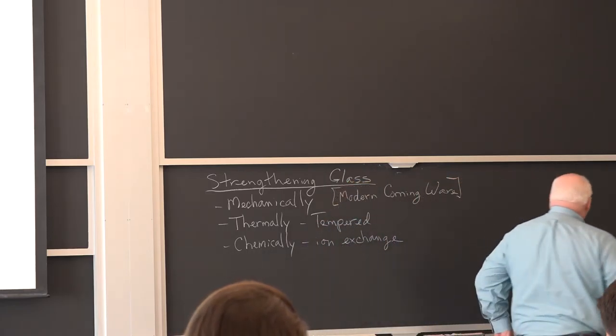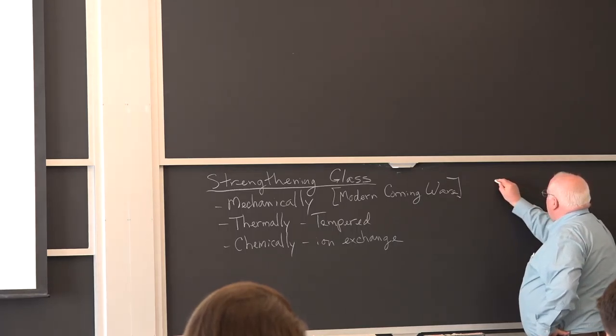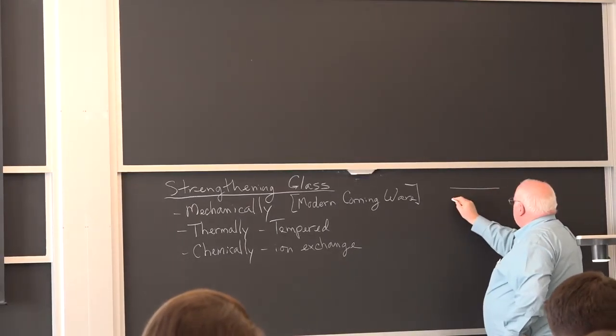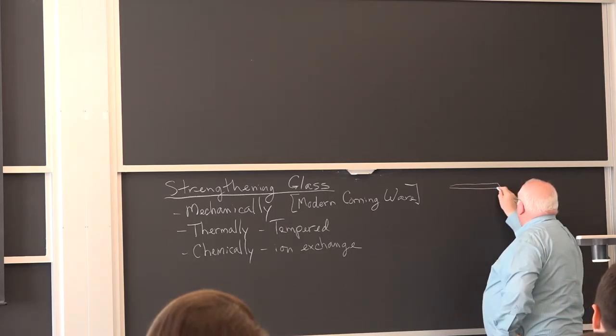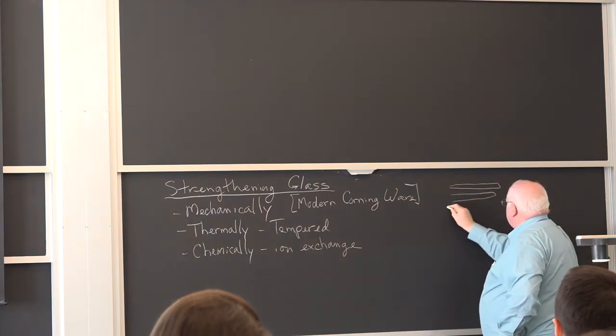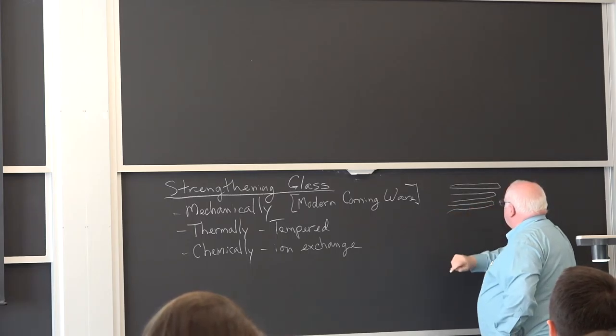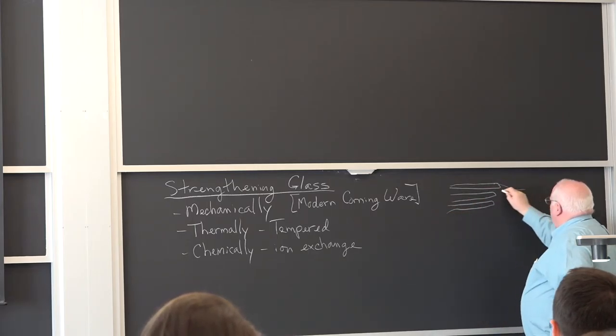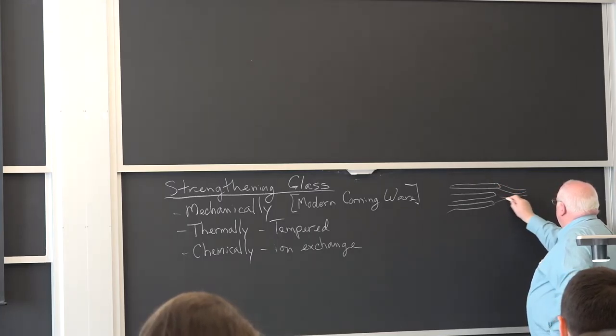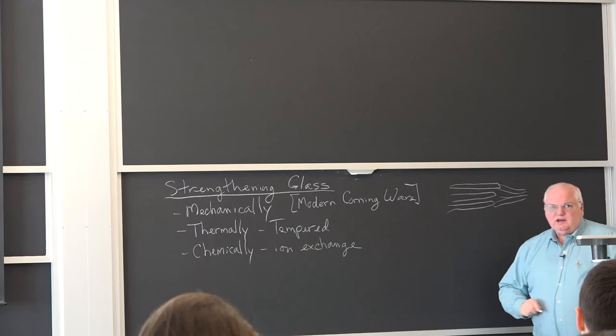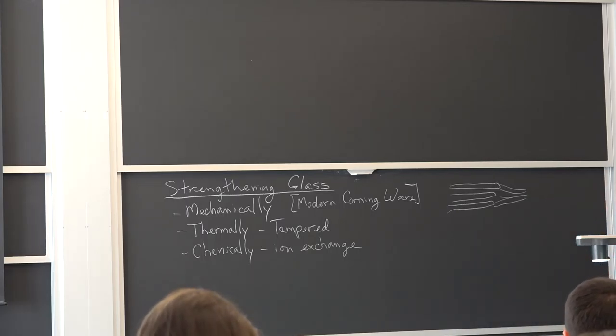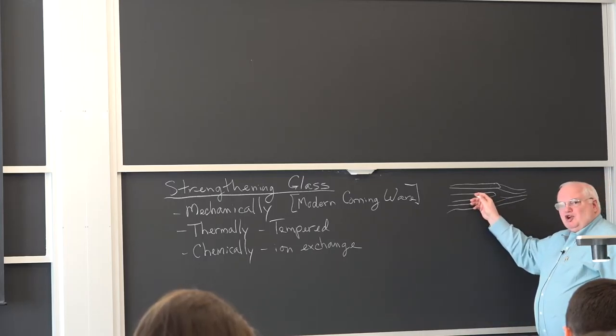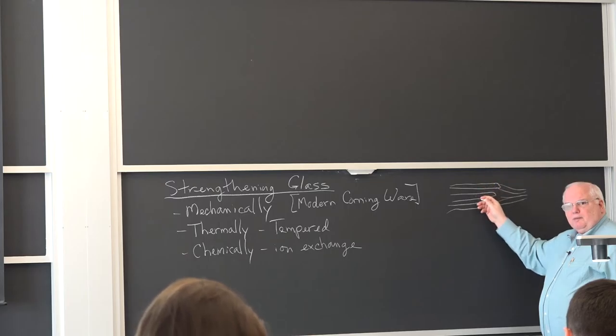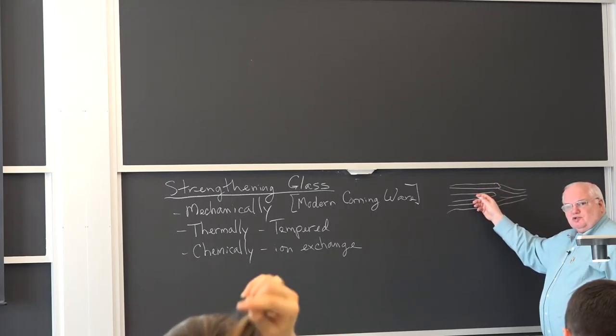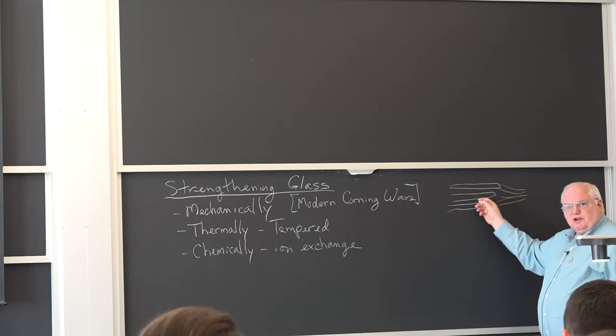There's also what Corningware did originally: they used a glass ceramic that had a very low coefficient of thermal expansion. But that was fairly expensive. But then modern Corningware, and Corningware has sold this process to another company, Corningware likes to get out of the business after a while, they had three different layers of glass. And they'd bring them in and they'd roll them together. And the two outer ones had a different coefficient of expansion than the center one. And when it cooled down, the one in the middle would contract more than the two on the outside, and you would end up with a tensile residual stress in the center and a compressive residual stress on the surface.